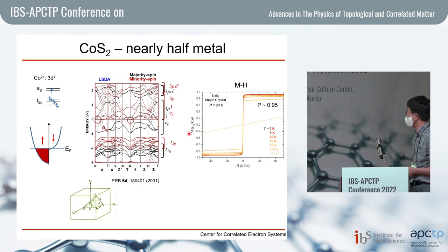magnetization and pull out the magnetic moment per cobalt, it turns out to be 0.95. So this is very close to one Bohr magneton, meaning that this single electron in each band is almost in the majority spin, but hardly in the minority spin. So this is very close to half metal. And usually, if you have half metal, then you can expect large anomalous Hall conductivity,